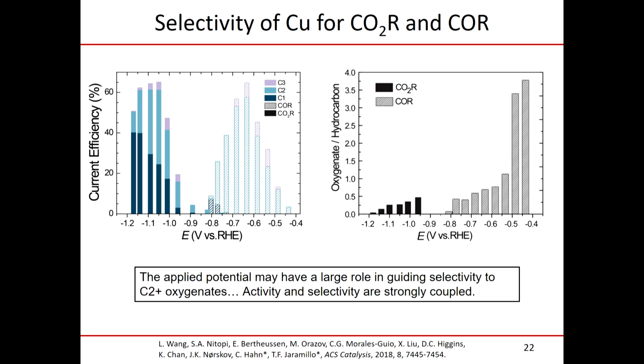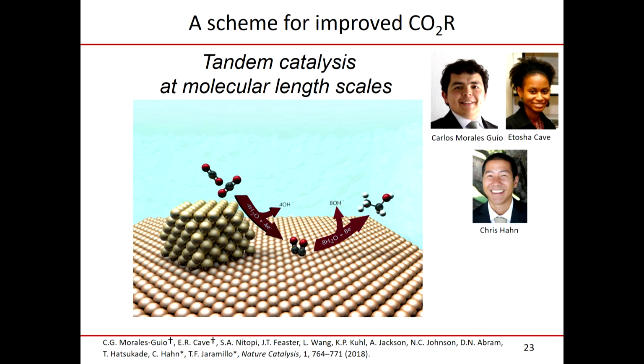Another point to take home is oxygenate versus hydrocarbon ratio, which is the plot on the right. When you're doing CO reduction, you see a lot better oxygenate production relative to hydrocarbons than you do in CO2 reduction. And we think this is really a simple reason. The closer you operate to the thermodynamic equilibrium potential, the less reducing power you have. And so you're going to have a better chance at making oxygenates if you're to the right of this diagram than when you're on the left. Now, how can we use all that information to design better catalysts? So here's Carlos and Etosha, who started putting gold nanoparticles down onto copper. Mark had also mentioned that gold is a very good catalyst for CO2 reduction to make CO selectively.